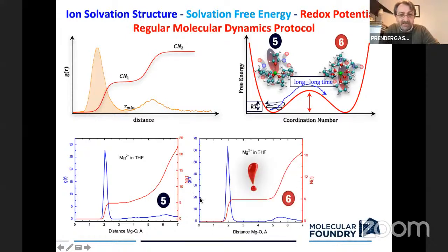But then if you begin the same simulation starting in coordination number 6, so a more packed region around the magnesium, you can also collect very stable statistics for the G of R and the coordination number. So you may have done a good job, in quotes, by running a long enough simulation, but that doesn't necessarily mean you have the answer, because clearly it depends on the starting point.